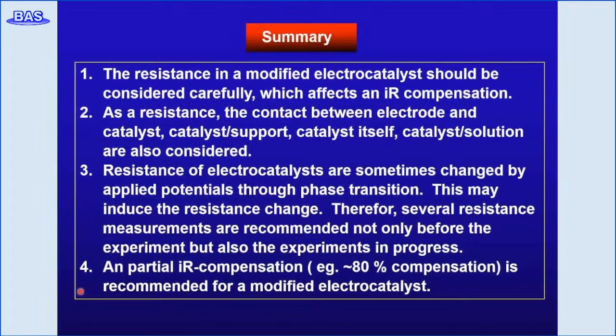Here is a summary of today's talk. The resistance in a modified electrocatalyst should be considered carefully, as it affects the IR compensation. As resistances, the contact between electrode and catalyst, catalyst support, the catalyst itself, and catalyst and solution are also considered.